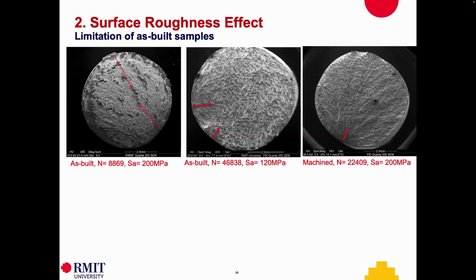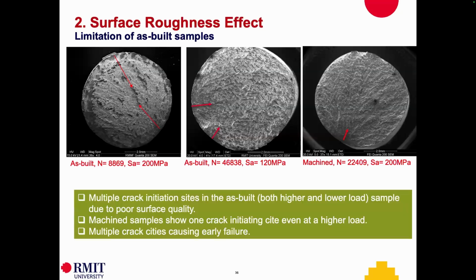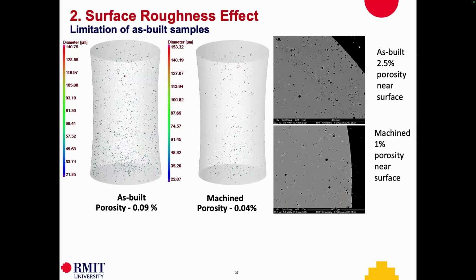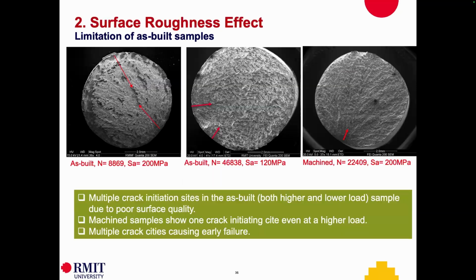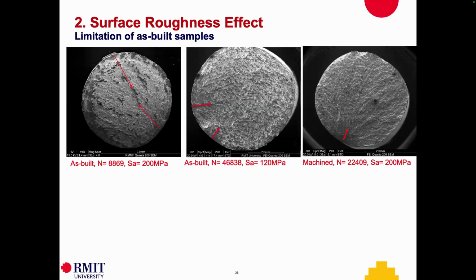Then we looked at the limitations of as-built samples. Fundamentally, you can see here multiple crack initiation happens, which causes fatigue failure for as-built samples. Whereas machine sample, we have a single crack. And you can see for the same stress amplitude, this is a single crack, which causes fatigue failure, there's a multiple crack. And that's what we can see. The machine surface has almost 3 times fatigue life.